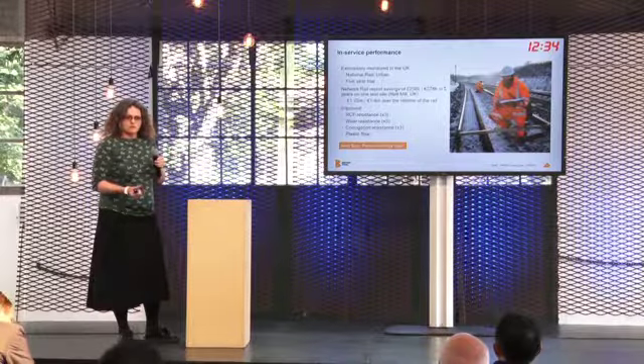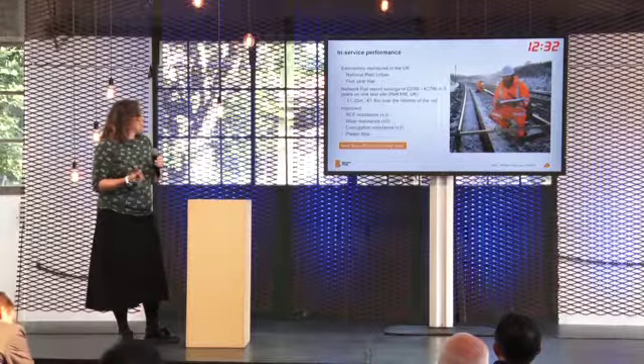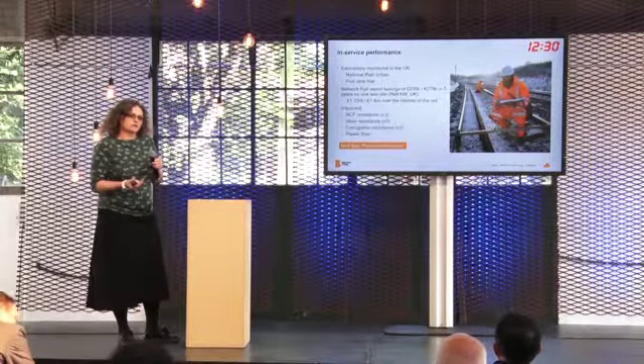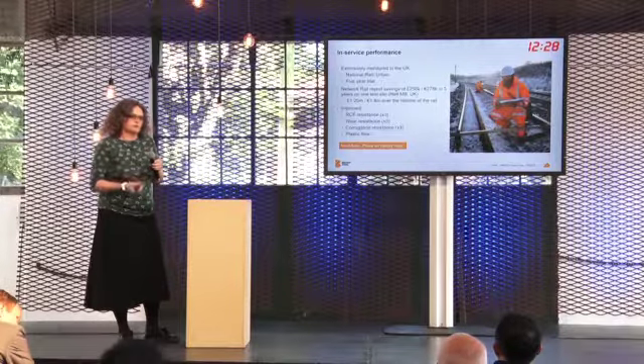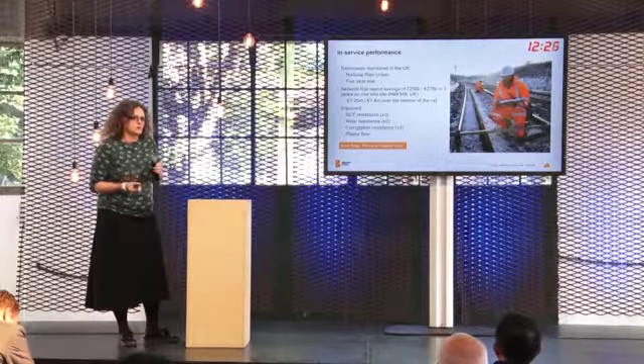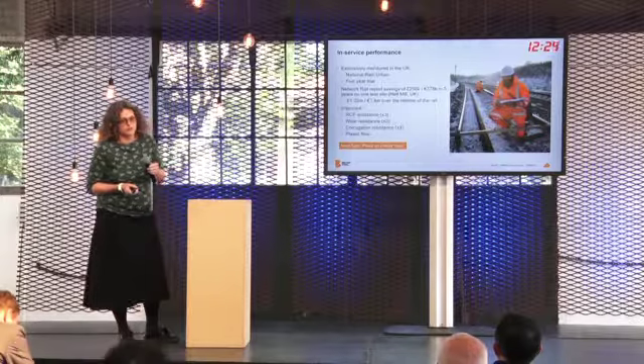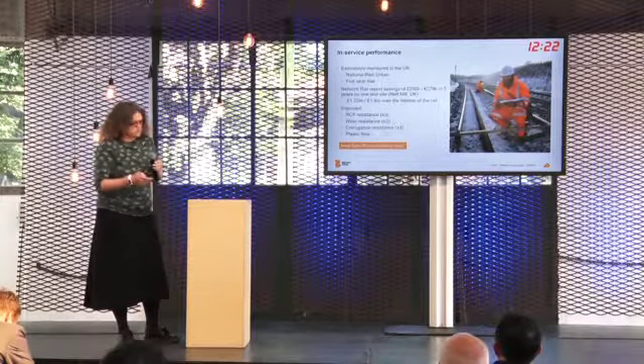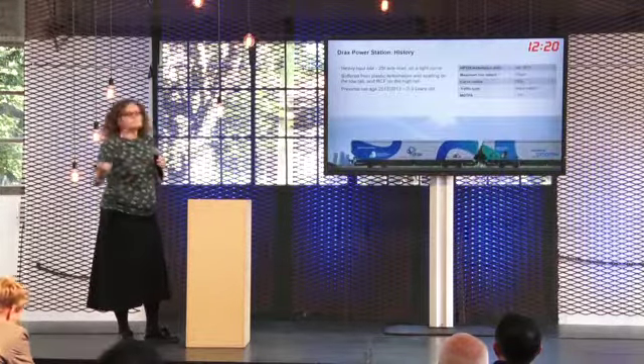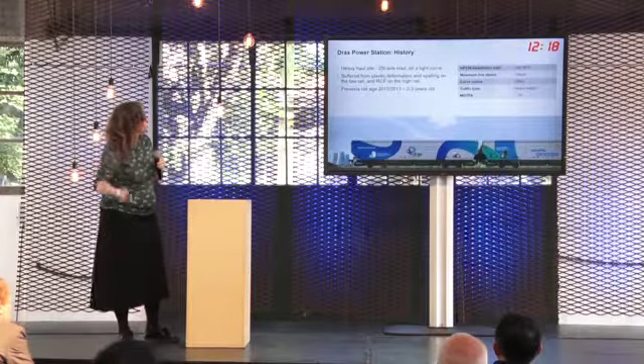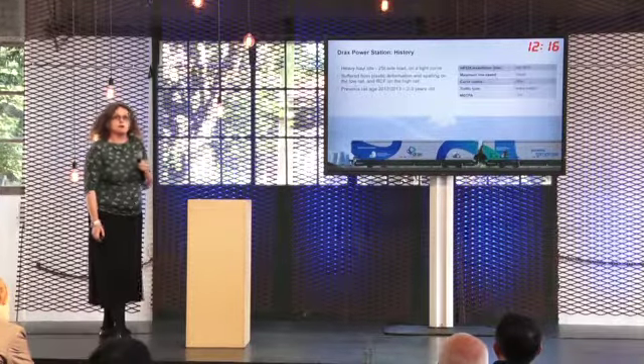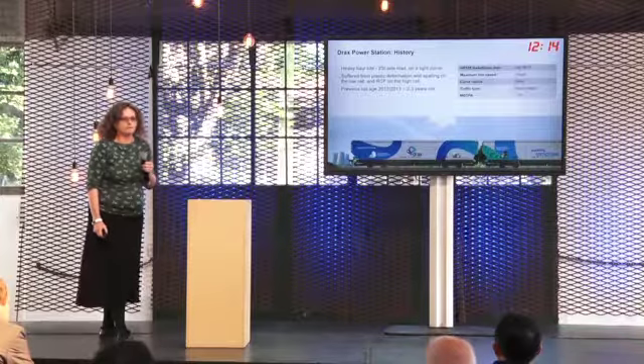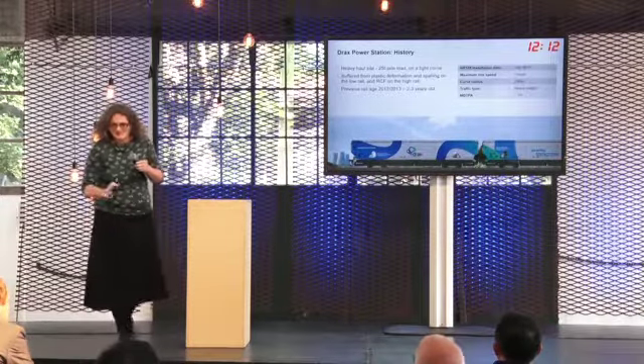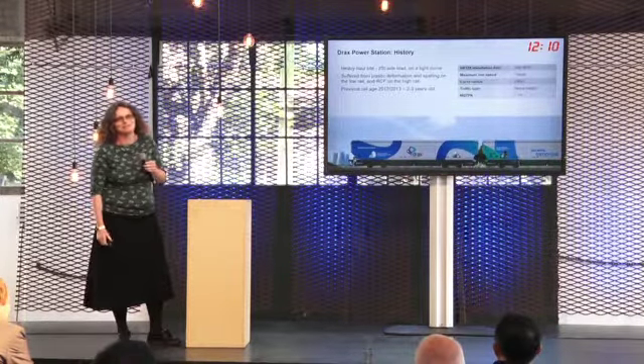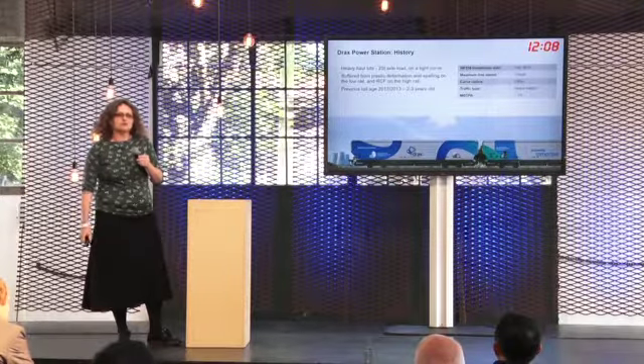The trial sites that we monitored showed that RCF, wear and corrugation resistance were improved by a factor of 3. We also found that resistance to plastic flow was very good. Out of all these trial sites, what we didn't look at was heavy haul. When I talk about heavy haul, in comparison to American railroads, it's slightly different. Our maximum axle tonnage in the UK is 25 tons.